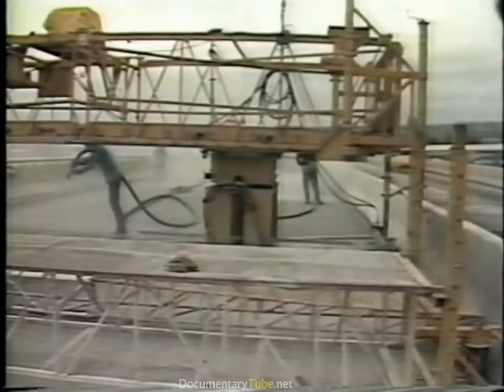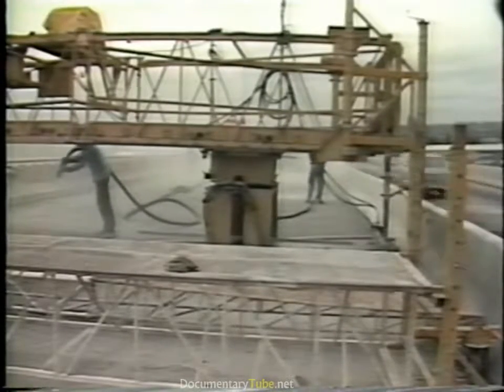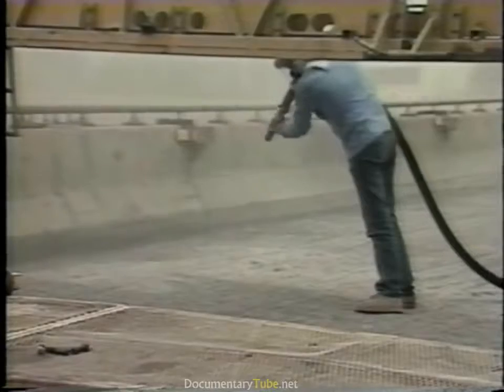After all of the deteriorated concrete has been removed, the remaining concrete and exposed steel should be blast cleaned. All contaminants, dirt, and loose rust must be removed so that a good bond between the overlay and the substrate may be obtained. High-pressure water blasting can also be used. This final cleaning must be done no earlier than 48 hours before placing the overlay.